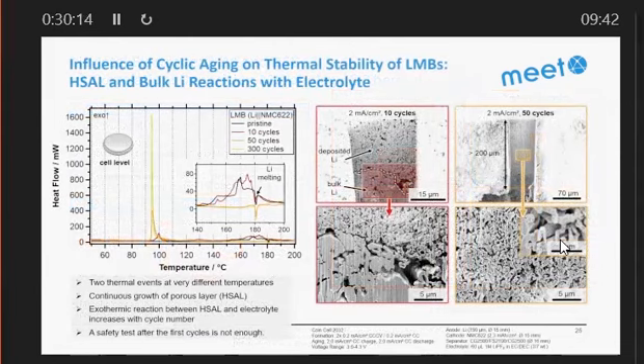So when we look at the thermal stability in DSC, we get two different responses. One at around 100 degrees C and less. This is the high surface area lithium. And the more cycles we have, the more high surface area lithium we have. And then there is remaining bulk lithium, and this bulk lithium reacts then when the SEI becomes soft and also it melts. This is around 170, 180 degrees C. And you see that the lithium melting also consumes some energy. And also you see that for 300 cycles, there is very little bulk lithium left at 180 degrees C, with almost a flat curve, because all the lithium is already high surface area lithium, and this reacts around 80 degrees earlier than the bulk lithium.